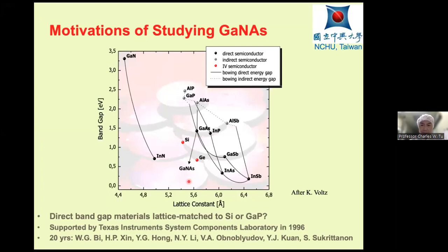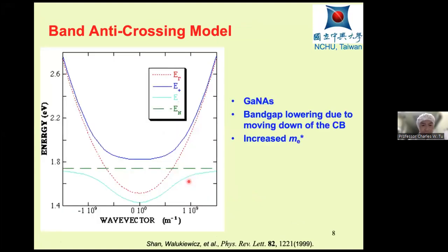To explain this, a band anti-crossing model was proposed. Here I plot the conduction band energy as a function of wave vector. This red line is the conduction band of gallium arsenide, and in the middle here is zero momentum, or zero wave vector. The horizontal line is the nitrogen energy level in the dilute limit. Because of the Heisenberg uncertainty principle, if nitrogen is isolated, we know its position well, and so its momentum cannot be determined. That's why it's a horizontal line like this.